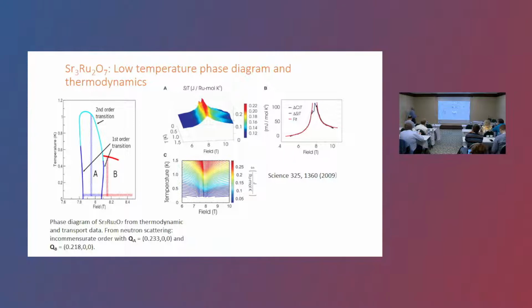Okay. You do get this if you have singular density of states. If you have a power law divergence, which can give us this 1 over H, for example, and also the insight is that if you have divergence in the density of states, then you may expect that the entropy here is higher than outside because you have so many states, and some of them are gapped because of the SDW, but you are left with so many different ones that you can have the entropy increased inside the ordered phase.